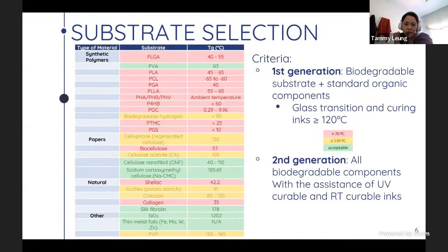The first of which was extremely important was requiring that the biodegradable substrates be able to handle curing temperatures above 120 degrees C. For this, I specifically tabulated the glass transition temperature for each of the considered substrates, or the glass transition temperature here is in reference to the temperature at which the substrate can decompose or begin to soften.